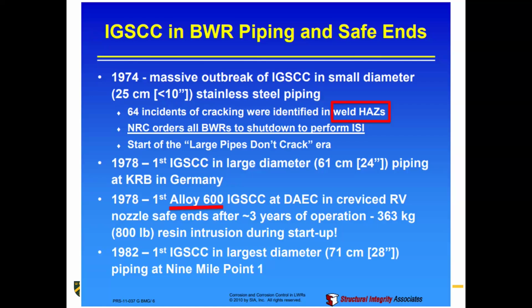And this started this general thought process that this is only a phenomenon limited to narrow piping. There were some reasons why at the time this was believed to be the case. This was so serious, though, that similar to what CANDU reactors experienced with hydrogen embrittlement within the zircaloy pressure tubing we talked about earlier in this course, this was a similar emergency where the material that we put in here that we thought was going to hold up is not holding up. So the main culprit here was 304 stainless steel rather than the zircaloy pressure tubing for CANDU reactors. But we were seeing this intergranular stress corrosion cracking.